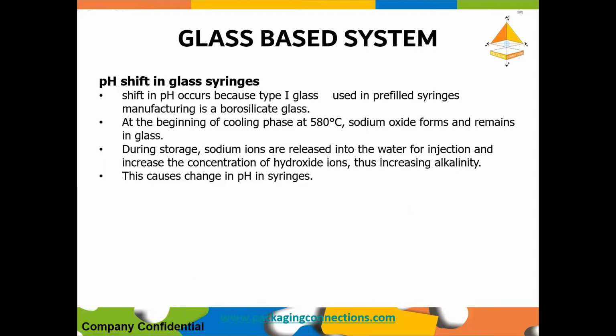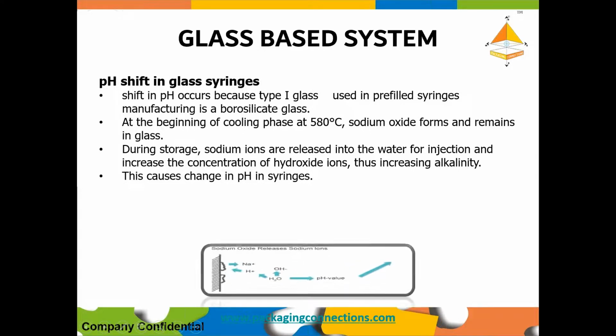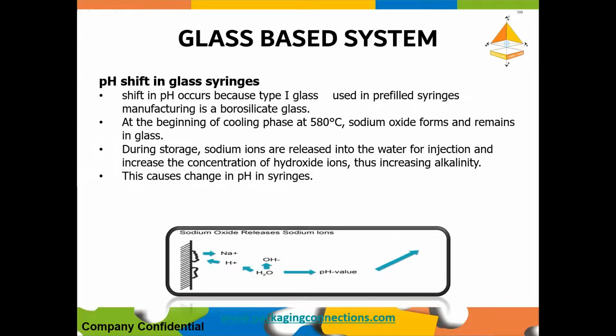In glass, there is also a challenge of shifting in the pH, because typically the PFS are made from type 1 glass, and initially when the heat is being applied and the forming is being done, during the cooling phase around 580 degrees, sodium oxide forms, and remains in the glass. So over a period of storage, sodium ions are released into the water or the diluent inside, which you can see here. Now the sodium ions are being released, and then there are hydroxyl ions inside from the water, and then the pH changes, which may not be good for some drugs.